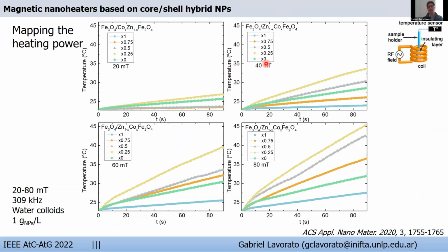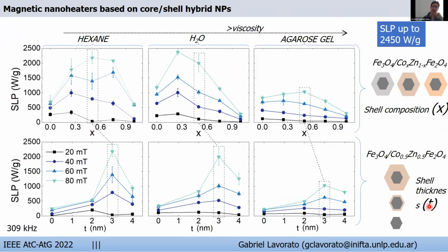Then our study followed by measuring the heating power in a calorimetric setup. The curves reveal large heating rates that increase for larger field amplitudes as expected. Then these curves were analyzed for the whole set of samples in 3 different media with increasing viscosity. So we found that intermediate cobalt concentrations or intermediate shell thicknesses provide a maximum heat, which is above 2000 watts per gram of material, under 300 kilohertz and different applied amplitudes.